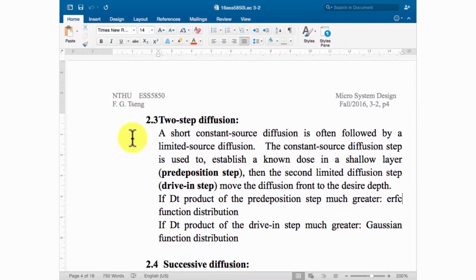The first step of diffusion we call the pre-deposition step. In the pre-deposition step, we usually bring the wafer in contact with a fixed concentration of the impurity source. So we allow a certain amount of the impurity to go into the substrate. Then we go to the second, drive-in process. The drive-in process has two purposes. The first one, we want to redistribute the concentration into the desired profile because we want the profile to become more uniform inside the silicon substrate.